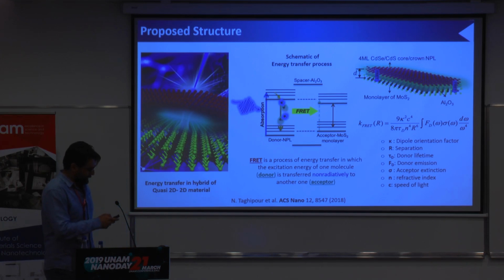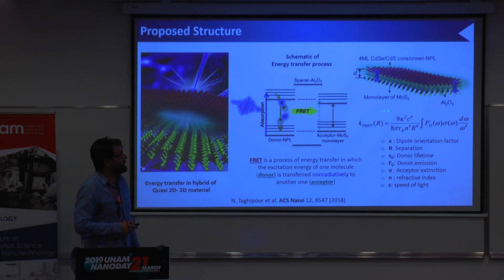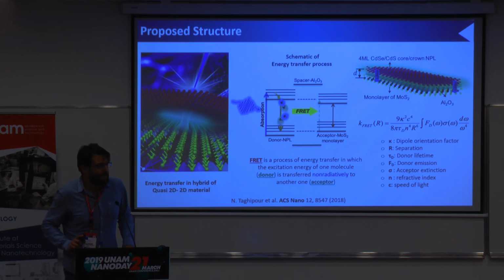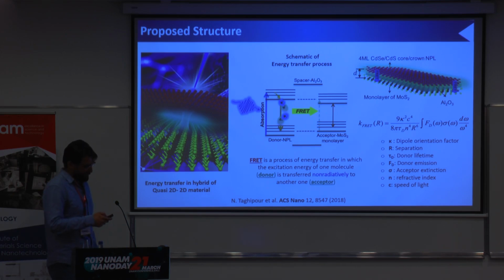The schematic of our proposal and the fabricated devices is shown here, where our colloidal nanoplatelets, quasi-2D colloidal nanocrystals, are separated by a dielectric spacer from a monolayer of molybdenum disulfide, which acts as a sinking layer for the carriers generated in our donor. Then the energy transfer process depends on a number of parameters you see here.